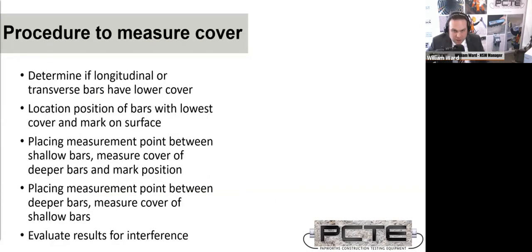Now, the procedure to measure cover. We don't know where the reinforcing steel is in a structure in most cases. It's rare you'd do a GPR scan before you use a cover meter. So we need to use the cover meter to find where the bars are and pick the best measurement points on those bars to get an accurate rebar depth measurement, a cover depth measurement. So the procedure is, first, we want to work out where our longitudinal or transverse bars have lower cover.